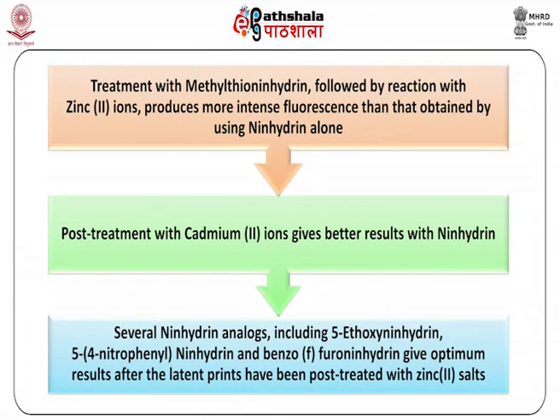Treatment with methylthioninhydrin followed by reaction with zinc ions produces more intense fluorescence than that obtained by using ninhydrin alone. However, post-treatment with cadmium ion gives better results with ninhydrin. Likewise, several ninhydrin analogues including 5-ethoxyninhydrin, 5-(4-nitrophenyl)ninhydrin and benzo(f)furoninhydrin give optimum results after the latent prints have been post-treated with zinc salts.